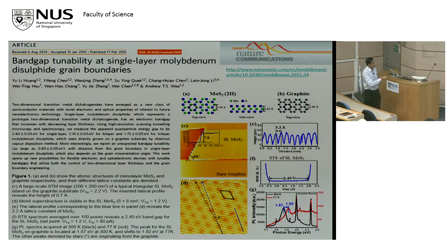It was basically showing MoS2 single layer on graphite. You can see a periodic, what we call moiré pattern, because MoS2 is not lattice matched with graphite. But it doesn't matter in these two-dimensional materials because the interactions are weak. That's why they're called van der Waals heterostructures. They don't bind covalently, so you can actually stack them and not worry about lattice matching.